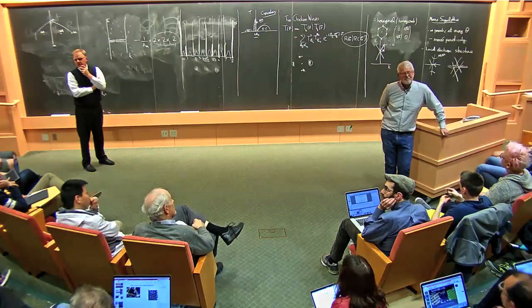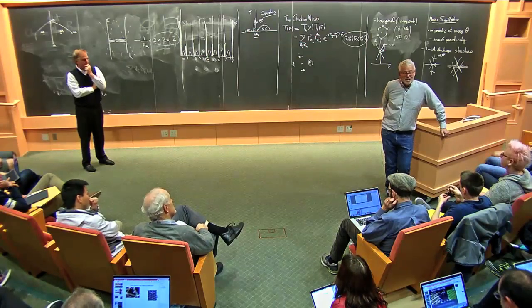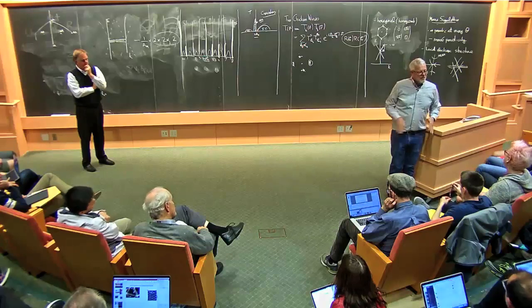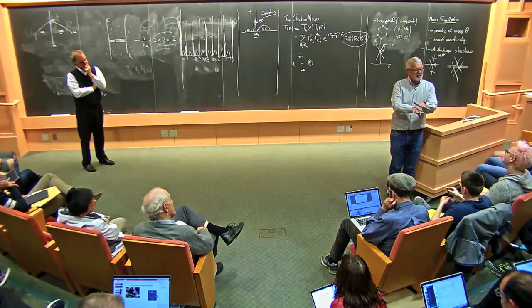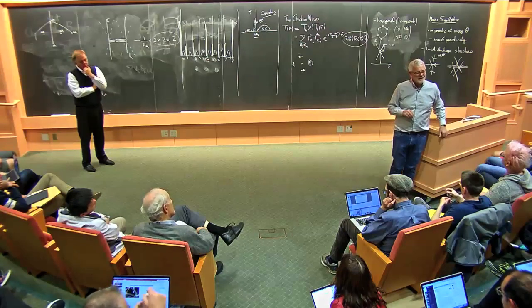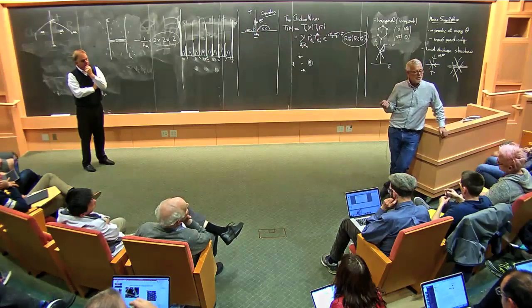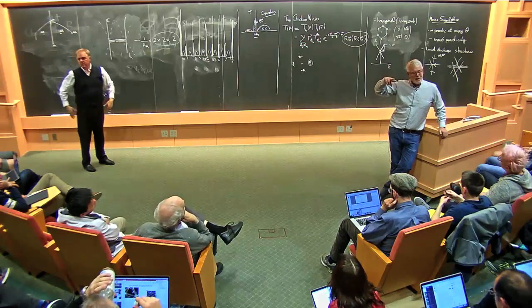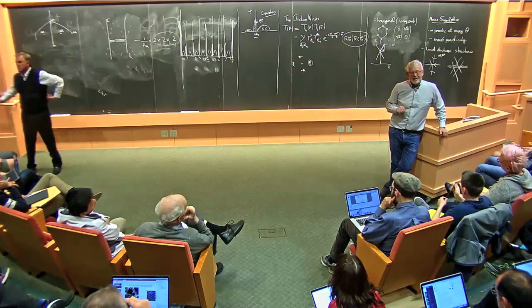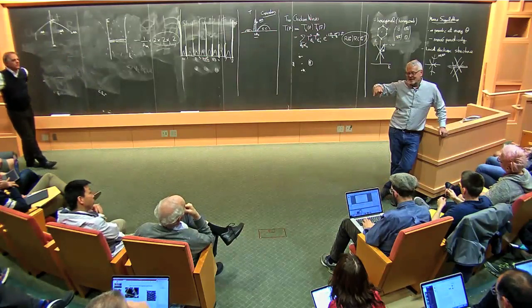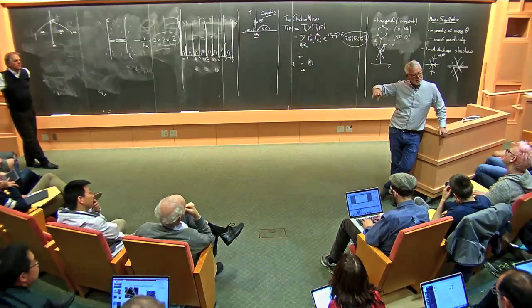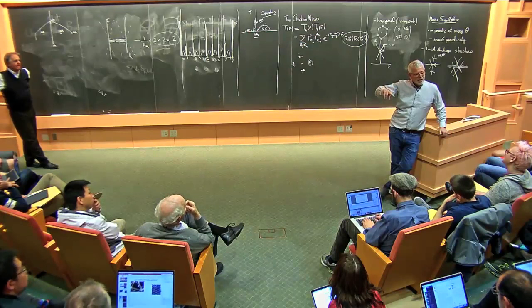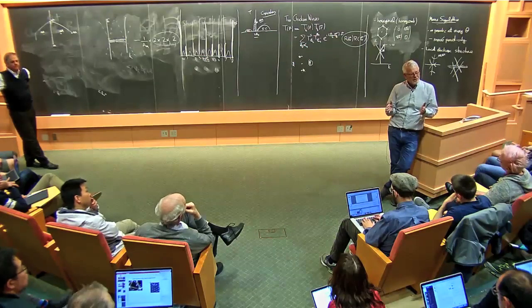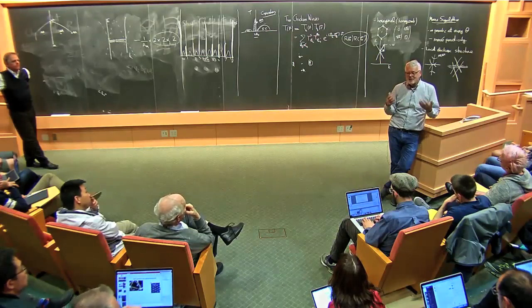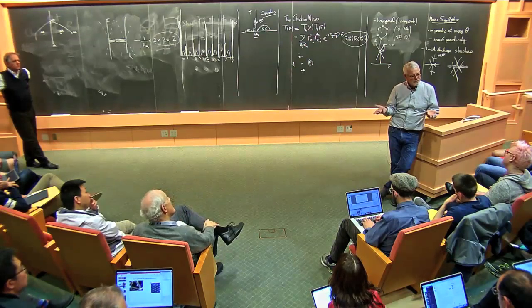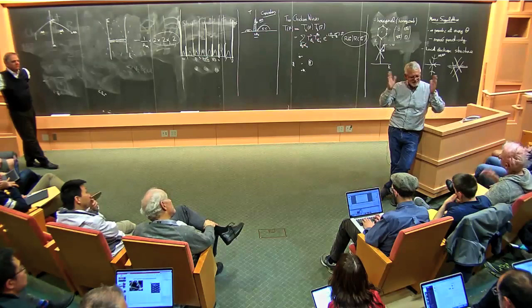Okay, and so as long as there's only one twist angle, you can take any graphene multilayer, take some group of layers and twist them, and this kind of stuff will happen. For example, one interesting case is where you have 3 layers. Then you can twist the top layer, or you can twist the middle layer. If you twist the middle layer, I think this is interesting from the point of view of superconductivity, because it turns out the middle layer couples to the symmetric combination of the outside layers. And it turns out the tunneling, the hybridization, is increased by a factor of √2, just because of the 1 over √2.